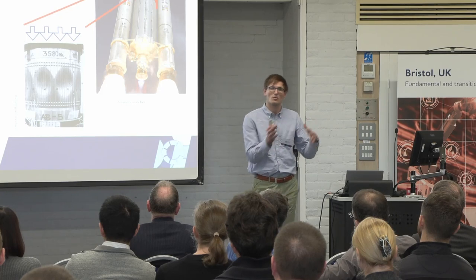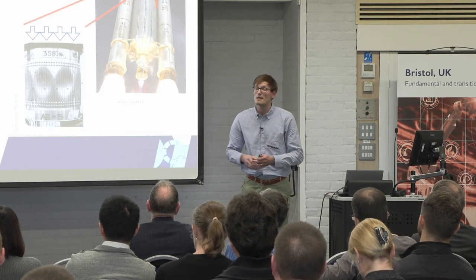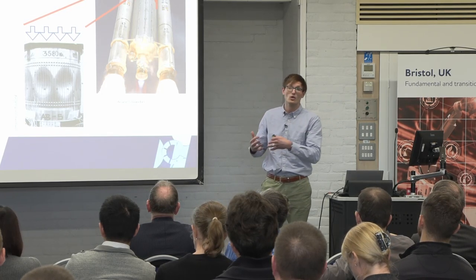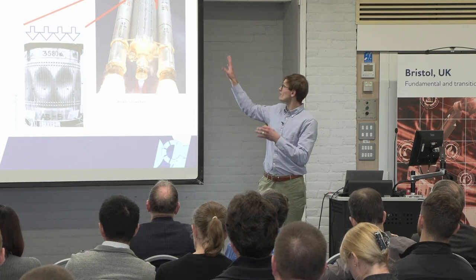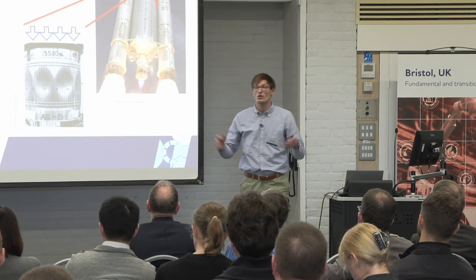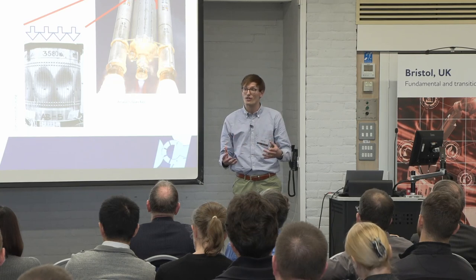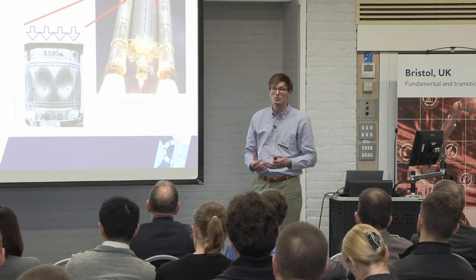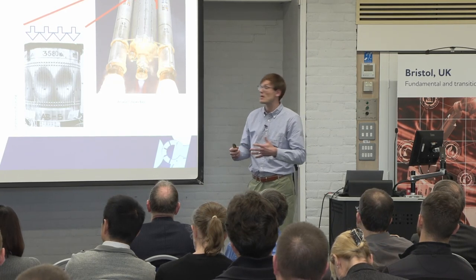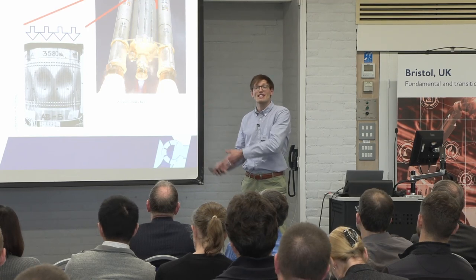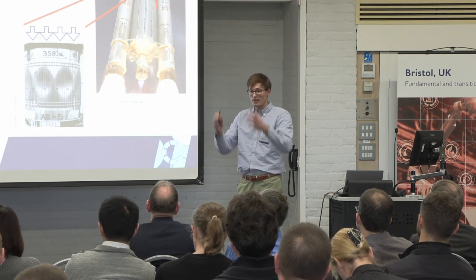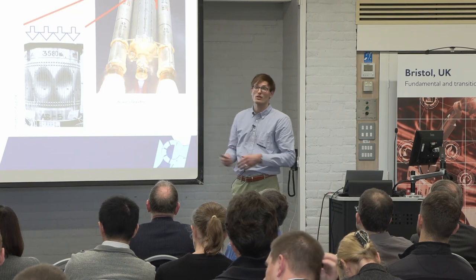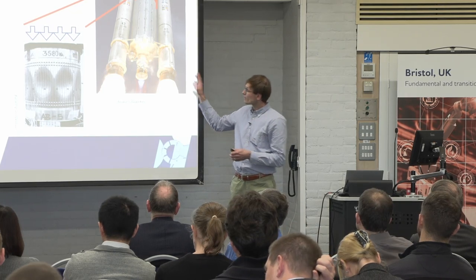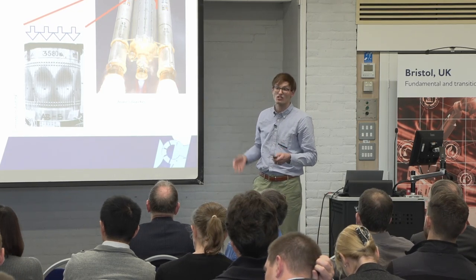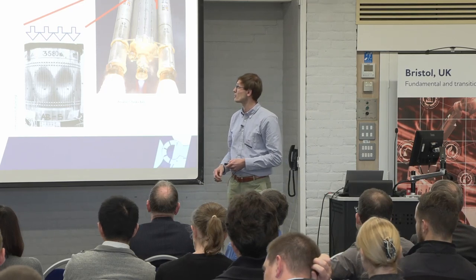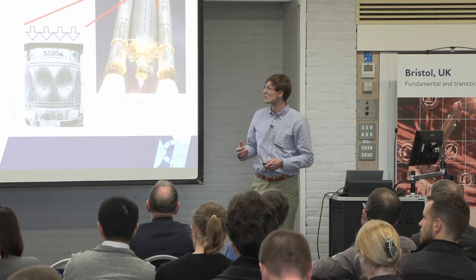Then there's the geometry and the structural side. If you try to minimize mass in these cylindrical structures, you're going to be reducing the wall thickness, trying to make things as thin as possible. That means that as these launch vehicles take off from the launch pad and are placed into compression with lots and lots of fuel in the fuel tanks, these sections just basically start to buckle, and that is the dominant failure mode of these structures.